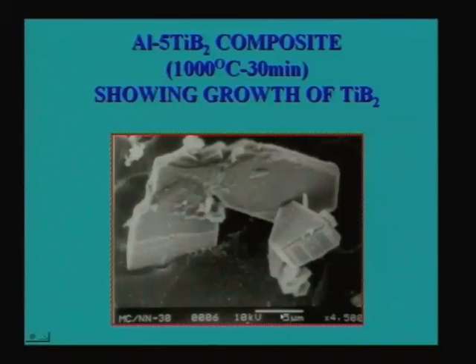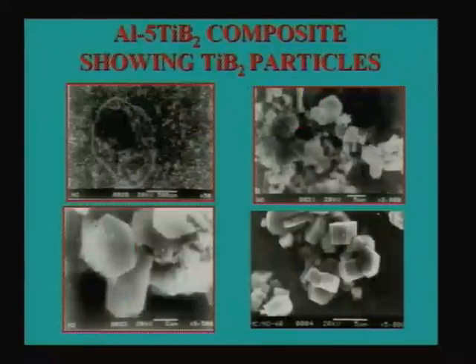And the growth morphology, we have talked about it. Basically the growth occurs on the basal planes of TiB2, because TiB2 has a hexagonal structure and the basal plane is the most close packed plane, so the growth occurs in the C direction. Once a nucleus has formed, the growth occurs in the C direction. And one can also make these composites with different volume fractions.